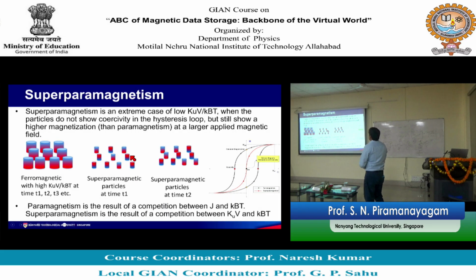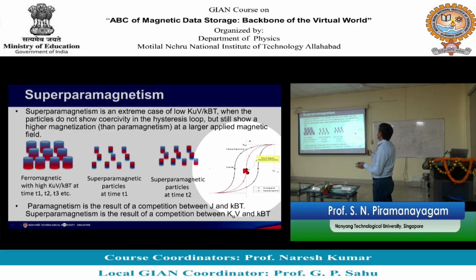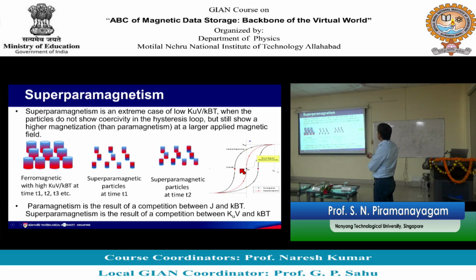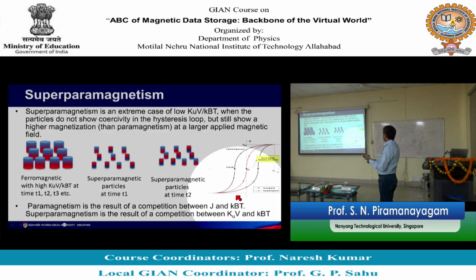Because the KUV by KBT is so small, the magnetization will keep fluctuating as a function of time. They do not retain the information. So, as they do not retain the information, that is why they have 0 Mr. At high field, you can force all of them to point in one particular direction, but once you remove the field at room temperature, they will be at a random direction. So, the net magnetization will be 0 at 0 field. So, we can say that paramagnetism is a result of competition between the exchange energy and KBT, Heisenberg exchange integral and KBT, but superparamagnetism is a result of competition between KUV and KBT.